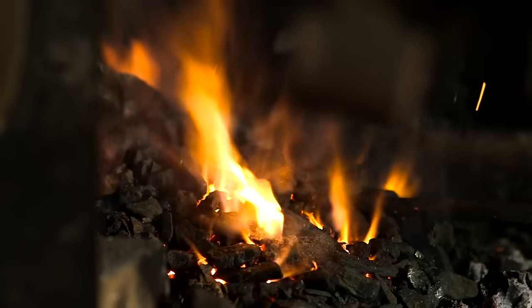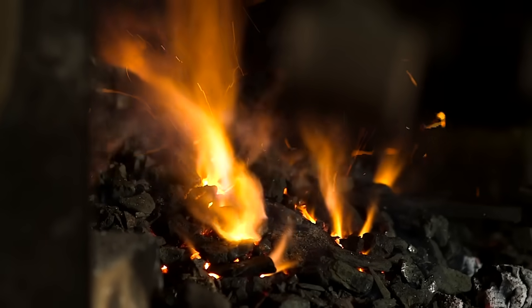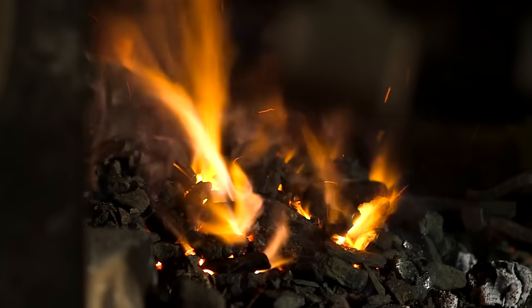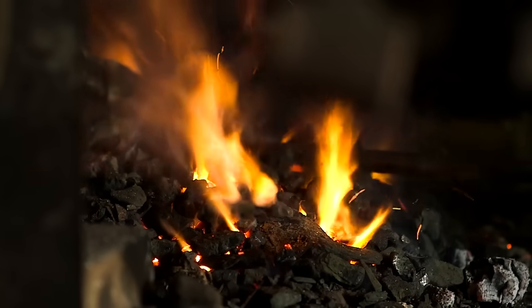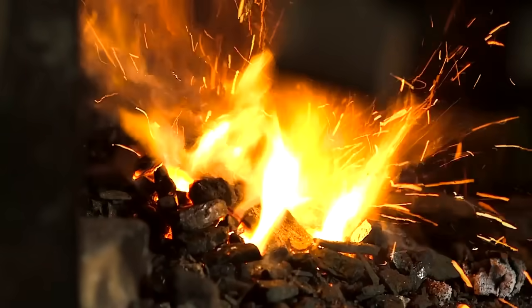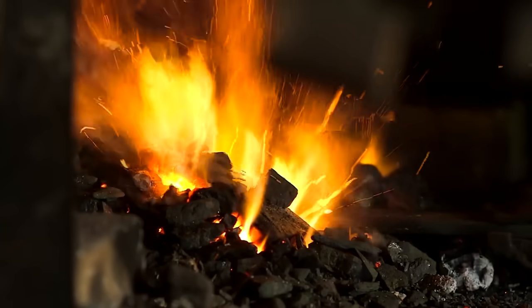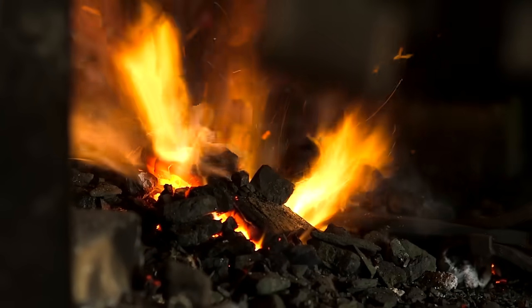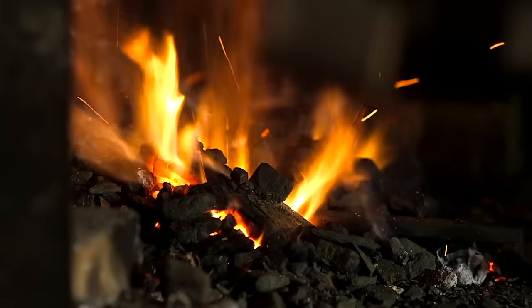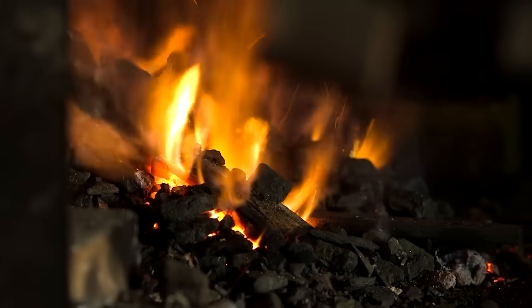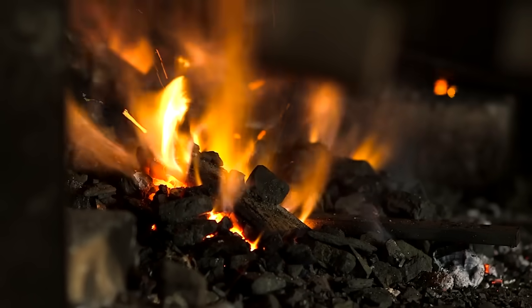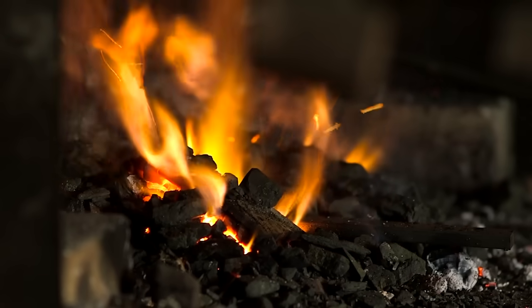When you plunge red-hot steel into pure water, something problematic happens. A layer of steam forms instantly around the metal. This steam envelope acts as insulation, slowing the cooling rate. If the steel cools too slowly, it will not harden properly. Salt solves this problem. The particulates in salted water or in urine disrupt the steam layer before it can fully form. The liquid maintains direct contact with the hot metal. Cooling happens faster. Hardening succeeds.